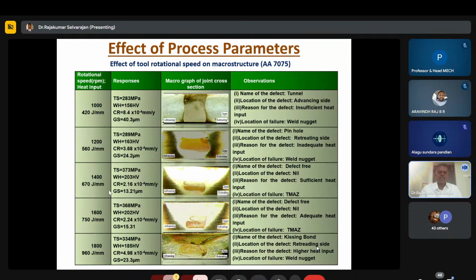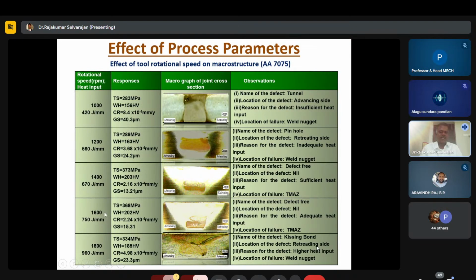The heat input was measured as 670 joules per mm. You can see that the tensile strength of the joint is 373 megapascal, and there is no defect in the weld region. After welding, we go for the tensile test. It fails in the HAZ region only. There is no defect because the sufficient heat input is suitable for defect free joints. Again we increase the welding rotation speed to 1600 RPM.